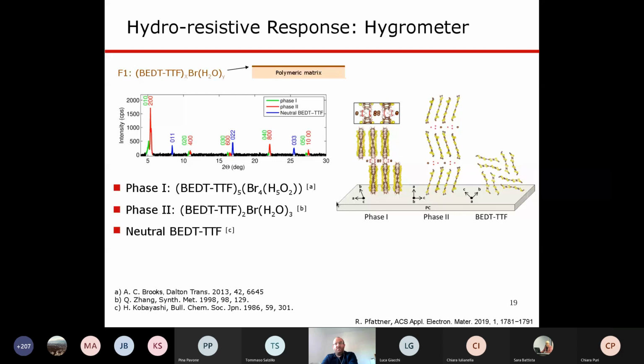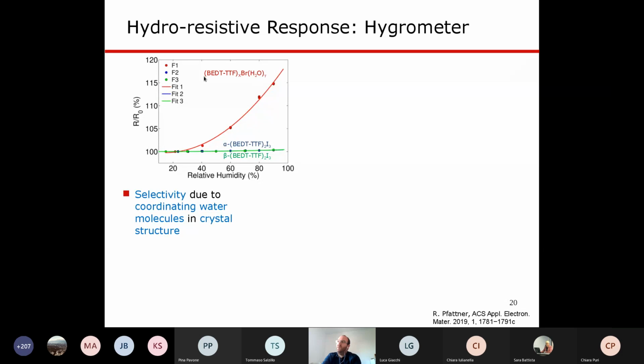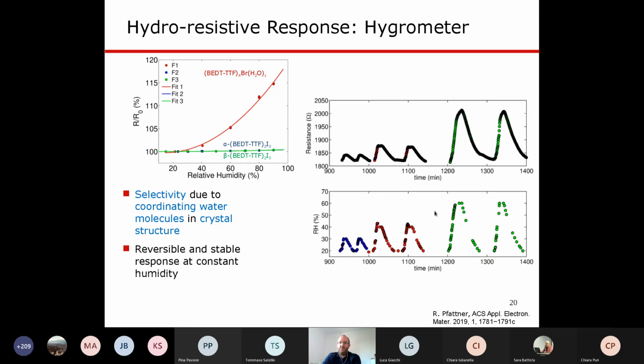Now, we wanted to see if this works as a humidity sensor. We had the suspicion that this could work. So we prepared different films with water molecules included in the crystal structure, but we compared them with different molecules that don't have these water molecules inside. And as we expected, only those with coordinating water molecules in the crystal structure show a response to humidity. The others were not responsive. This is very nice again because we can try to make selective humidity sensors. We tried the reversibility and the stability. So on top over here, you can see the change of the resistance. And at the same time, below, we measured the change of relative humidity. So you can see very nicely how the resistance now follows the relative humidity.